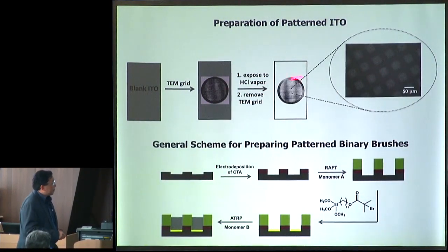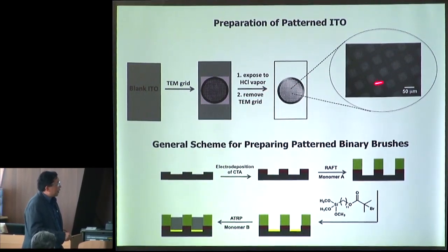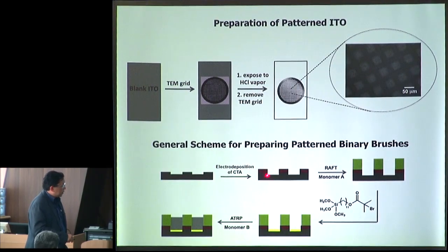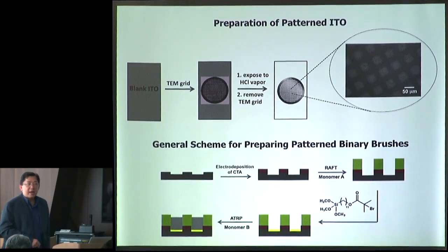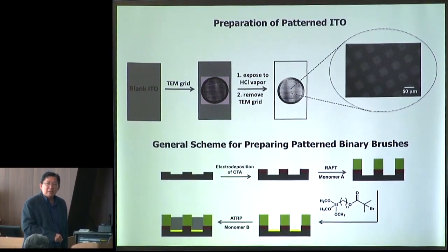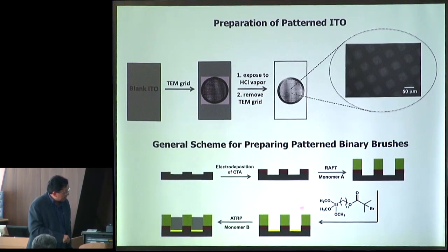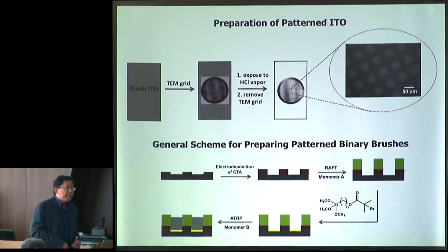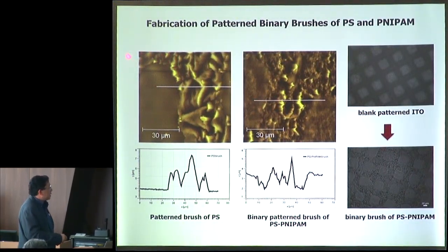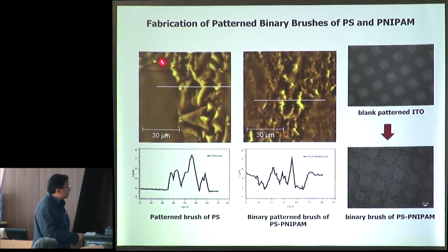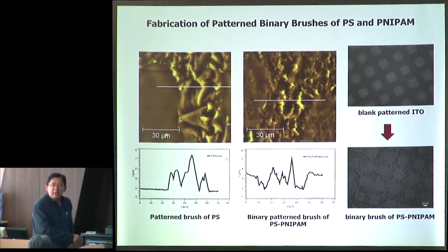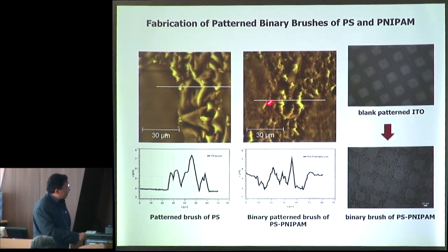So we did that, for example, with a simple pattern, a patterned ITO electrode, as shown here. So we would electrodeposit the chain transfer agent for RAFT. We would grow the polymer brush by RAFT, and since the middle part is still ITO, we can then add another initiator for ATRP in the middle, and then grow another polymer brush by ATRP. So in essence, we can make 2 types of polymer brushes within these patterns. And to prove that, here we have an AFM of polystyrene. But then after the fixation of the ATRP initiator, we will grow poly-NIPAM right here. So this original pattern was translated into this pattern.